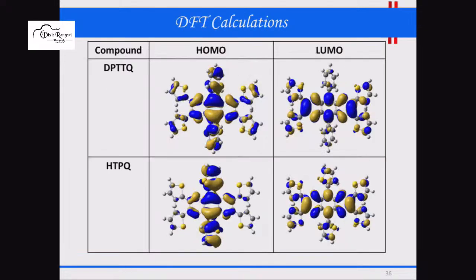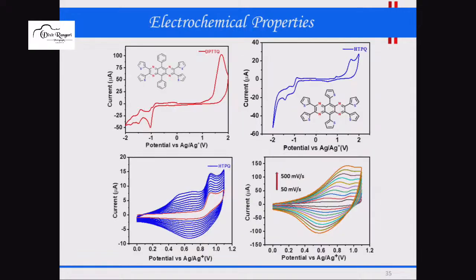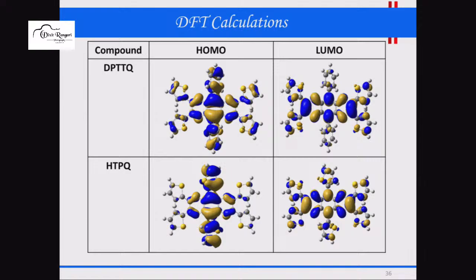So then we did a simple DFT calculation and looked at the HOMO and LUMO. Now if your oxidation process is going, that means you are taking one electron out of the HOMO, so you have to look at the HOMO. If you see the HOMO of both molecules, there is electron density only on the thiophene rings which are in the vertical direction. I can show you the structure again. In the vertical direction, there is a phenyl ring here, and in the next molecule, thiophene. Where is your HOMO density, at phenyl or thiophene? You see the thiophene on the vertical axis, that thiophene is the only one active for the electropolymerization.